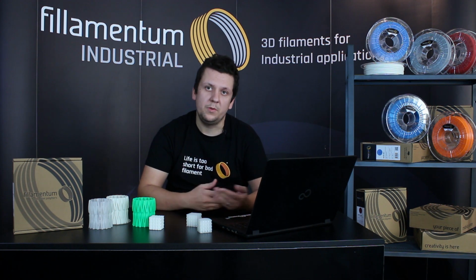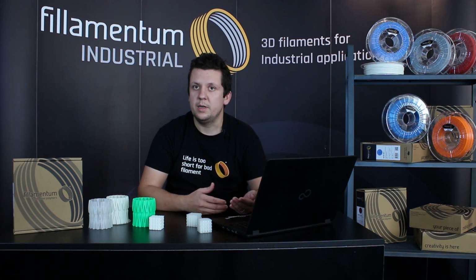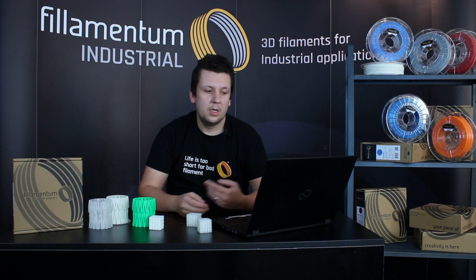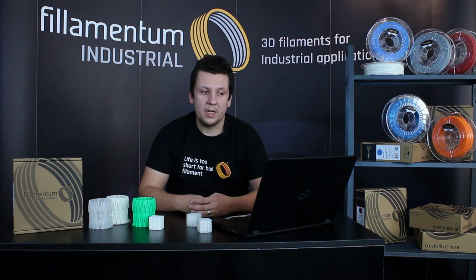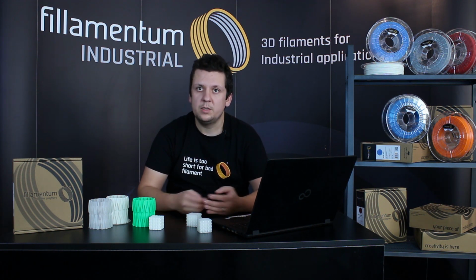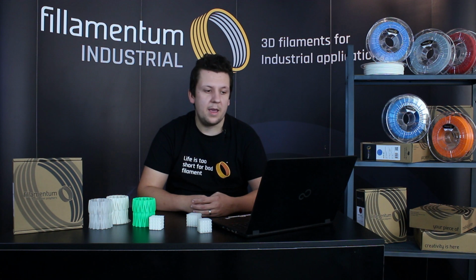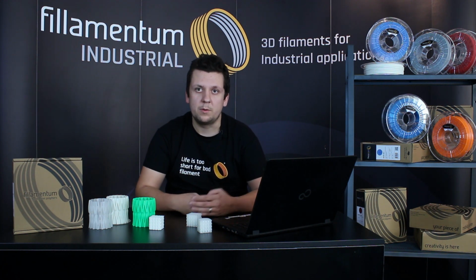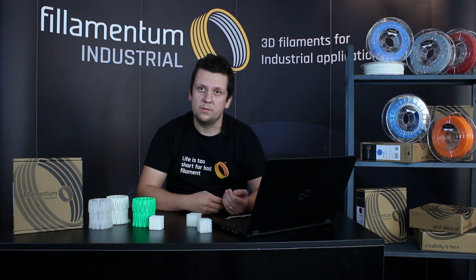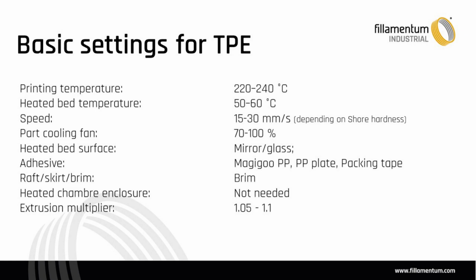Well, sometimes it happens that you have a wet filament, so depending on the hardness of the filament from our portfolio, if you have 98 Shore A or 92, the drying temperatures are 100 degrees Celsius for 3 hours for the Flexfill TPU 98 Shore A, and 80 degrees Celsius for 3-4 hours again for the softer variant, 92 Shore hardness.